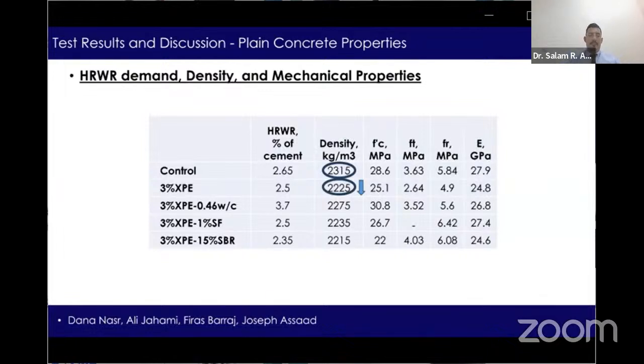The drop in the mechanical properties due to XPE additions is very clear in this table. This drop was recovered when the water to cement ratio was reduced from 0.55 to 0.46. So for example, if we look at mix 3 containing 3% XPE and a reduced water to cement ratio of 0.46, we can notice that f'c, for example, reached 30.8 megapascal and fr reached 5.6 megapascal. So we can conclude that reducing water to cement ratio is an appropriate alternative to refine the matrix porosity and ensure strength development.